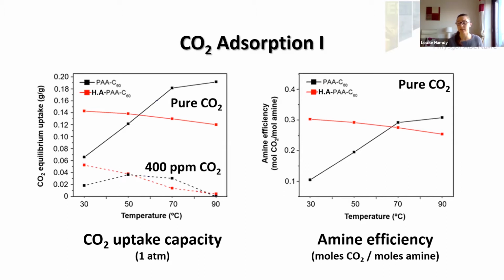Looking at the amine efficiency in this graph, we see that the amine efficiency of the hydrophobic additive material is very high at 30 degrees, and it's far more temperature dependent for the non-hydrophobic additive material.